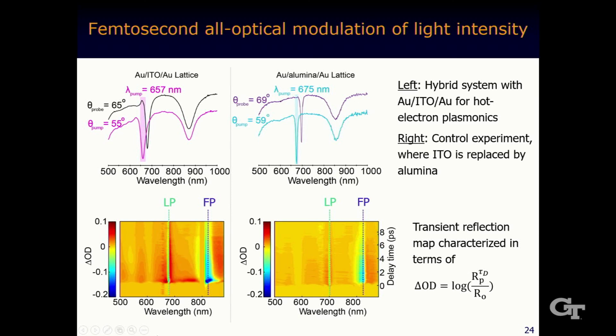Then we vary the time delay, also using a broadband probe light. So it's modified by this one, delta OD, the change in the optical density. And you can see that in this case, indeed, the reflection of light from this entire device, which also translates to absorption of light, can be modified by the pump light. This horizontal axis is the wavelength of the probe light, the vertical one is the OD. And you can see it's particularly pronounced when you hit the resonance.